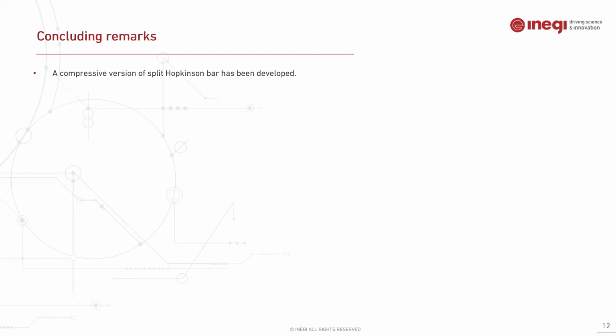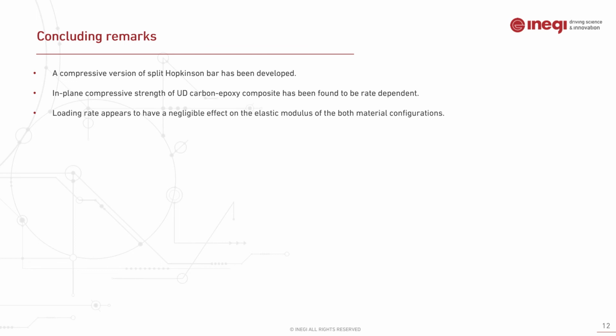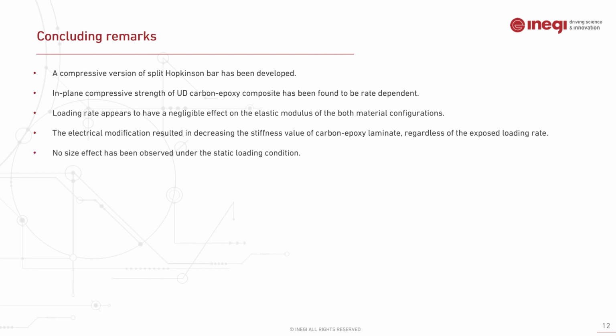So in conclusion, we developed a compressive version of the split Hopkinson bar to characterize composite materials, and we found that the in-plane compressive behavior of the carbon epoxy composites is quite rate dependent, while the elastic modulus of the material appears to not be affected by the loading rate. And also the electrical modification of this material appears to lower the stiffness value of the carbon epoxy composite regardless of the loading rate. And finally, no size effect was observed under static loading conditions.